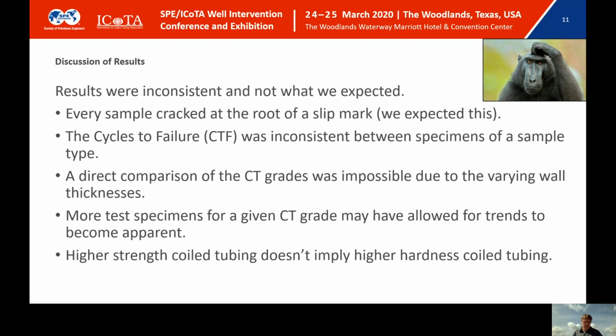So, here are some of our learnings from the results. We were a little disappointed with the inconsistency of the results initially, but we did find that every sample cracked at the root of a slip mark, and that's what we expected to see. The cycles to failure had quite a range from sample to sample, even within the same specimens. A direct comparison of the coil tubing grades was very difficult given the varying wall thicknesses. More test specimens for a given coil tubing grade may have allowed for the trends to become more apparent.